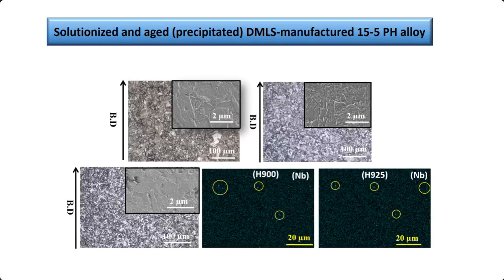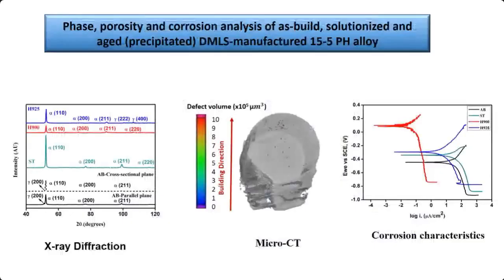So we tried to implement the same kind of heat treatment used for conventional testing, and we could see the precipitates come out at such temperature changes. We figured out the optimum heat treatment needed for these additively manufactured materials - if we want to use this precipitation hardened steel, we should use this optimized heat treatment so we can have the best of all the properties.